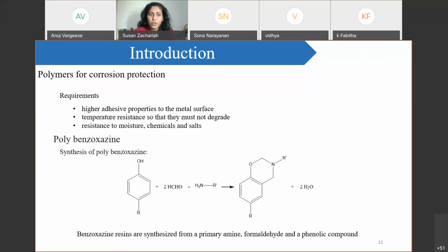Now, polymers for corrosion protection. The requirement of the coating polymer is that it should have high adhesive property to the metal. Even if we use a superhydrophobic polymer on the surface, it should adhere properly to the surface, or else in application it may peel off. So adhesion of the polymer is one of the major requirements. Temperature resistance, so that they do not degrade. Resistance to moisture, chemicals, and salts. The polymer which I have used for coating cold rolled steel is polybenzoxazine.